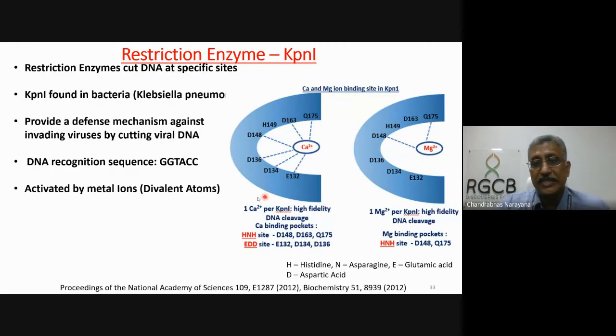So you can see that if you have calcium, this actually recognizes this sequence very, very precisely. If we put magnesium in smaller quantity, it recognizes this sequence. But the moment you put a higher concentration of magnesium, it becomes promiscuous. That means it doesn't look at only this sequence, it cuts anywhere and everywhere. So promiscuity increases when you have magnesium. Just the difference of a cation changes it.